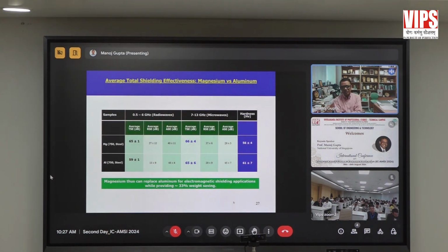So we worked on magnesium and compared it with aluminum, and we found that the radio wave shielding and microwave shielding of magnesium is similar or better than aluminum, which is commonly used for electromagnetic shielding. So I want to replace aluminum with magnesium. The reason: I make my phone lighter, I make my laptop lighter. I replace aluminum, which is a neurotoxic element, with magnesium, which is a nutritional element. So it's a win-win situation for me to use magnesium. And that is where the industry is trying to move.